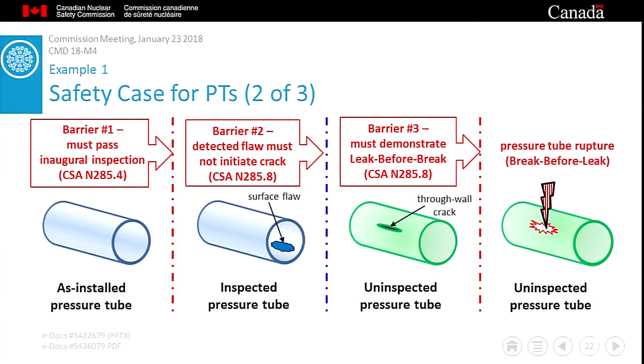An LBB assessment asks a simple question. Assuming a pressure tube has a crack and it has just begun to leak, would operators be able to identify the leaking pressure tube and safely shut down the reactor before that crack could grow to an unstable length? If the LBB assessment predicts that operators would be successful, CNSC staff agrees that LBB has been demonstrated and barrier 3 has been crossed. If, however, the assessment predicts that the crack would reach an unstable length before operators could shut down the reactor, staff refers to this situation as break before leak. And once again, I'd like to emphasize that while some Canadian pressure tubes have demonstrated leak before break, only one tube has ever demonstrated break before leak.